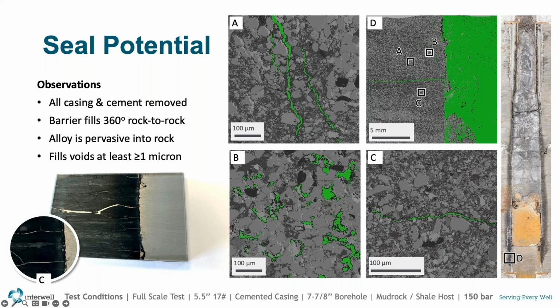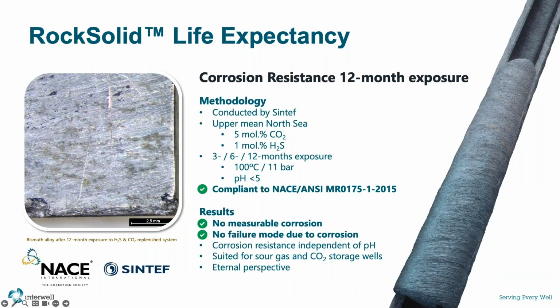Next slide, we'll talk about the corrosion potential or life expectancy of the barrier itself. So for this test, and again, as a part of our technology qualification, we sourced out a third-party organization to conduct this testing. Sintef was selected for this process itself. They were utilized to provide testing to test at 3, 6, and 12-month corrosion tests. They were conducted in a corrosive replenished system, 5% CO2, 1% H2S, temperature of 100 degrees Celsius, and 11 bar.